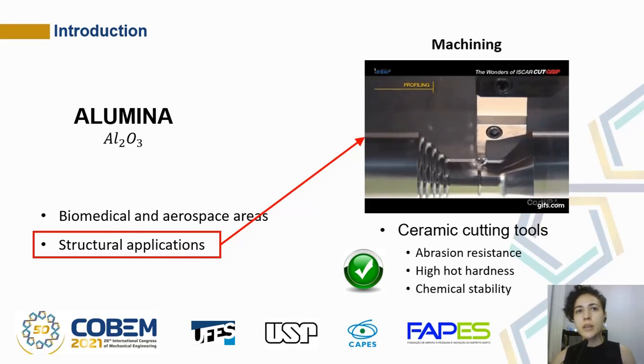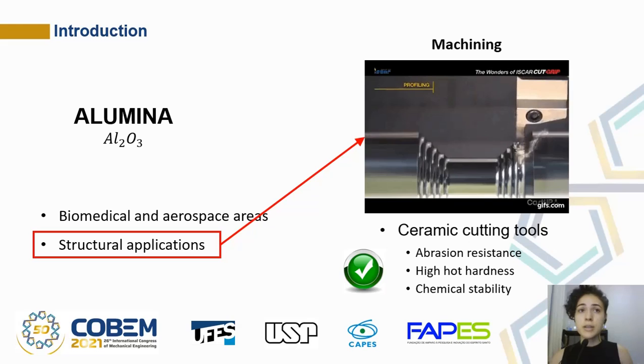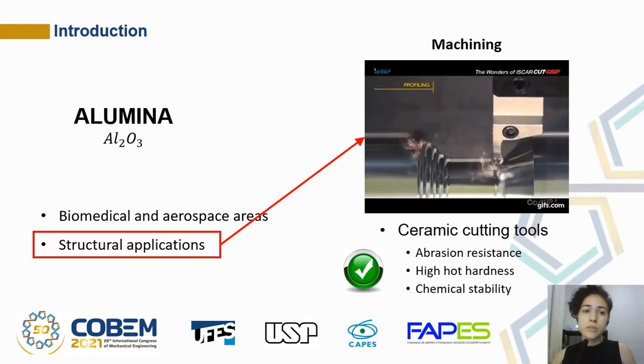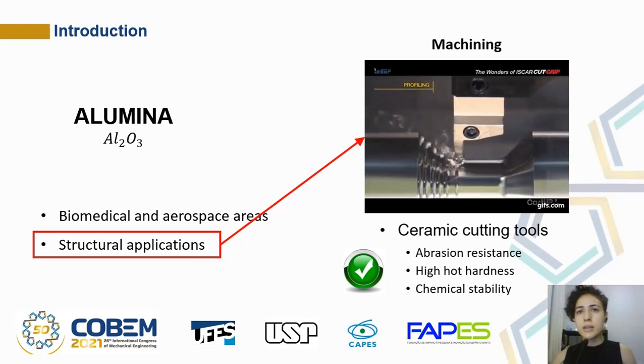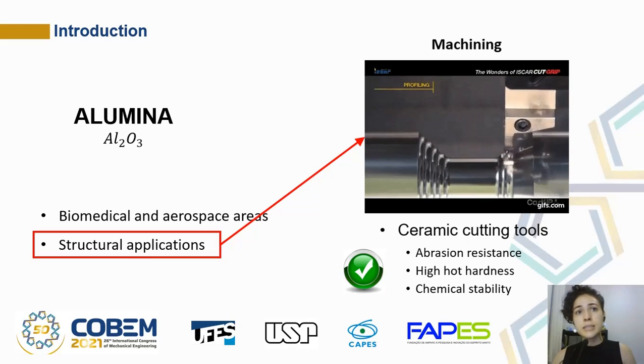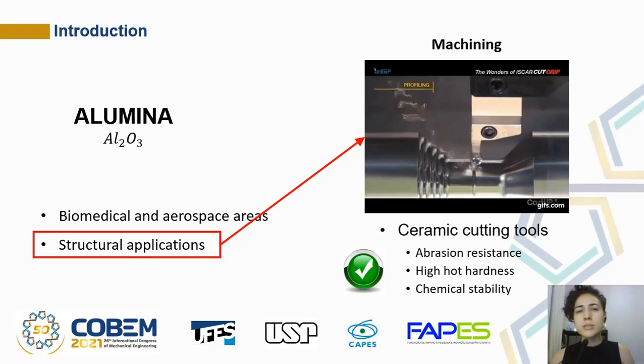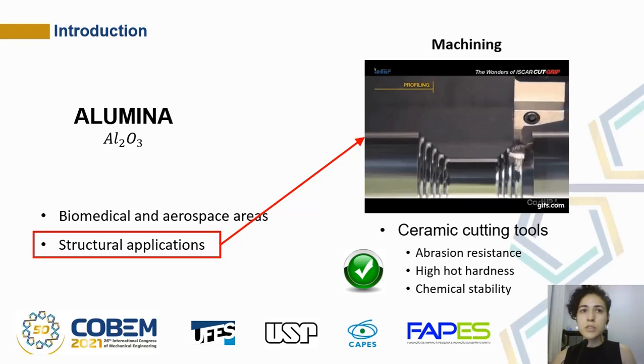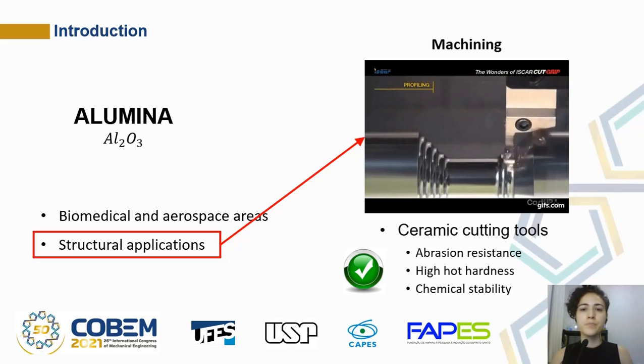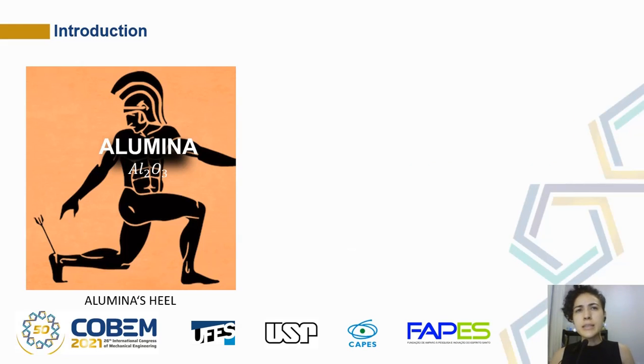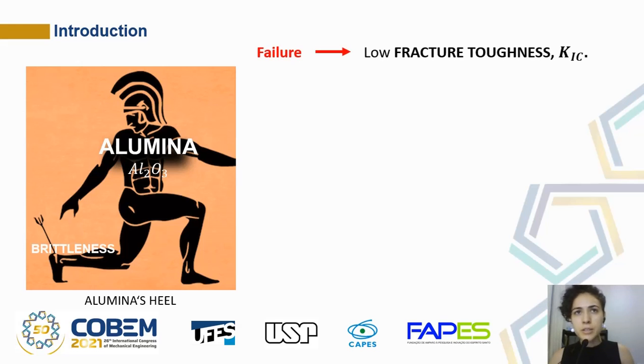In machining, in which environmental conditions are severe, ceramic cutting tools made of alumina have abrasion resistance, high hot hardness, and chemical stability, which reduce the tendency to adhere to the workpiece materials during machining. However, the Achilles heel of the ceramic, working under mechanical loads and thermoshock conditions, is the brittleness. And the failure under such service conditions is usually related to the low fracture toughness.